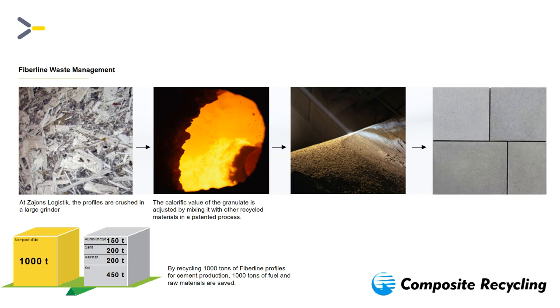By crushing FRP, the cement manufacturers use less coal, but also benefit from the glass reinforcement, which is then a raw material. There's a small figure on the left. By using 1,000 tons of GFRP scrap, they can save about 450 tons of coal.